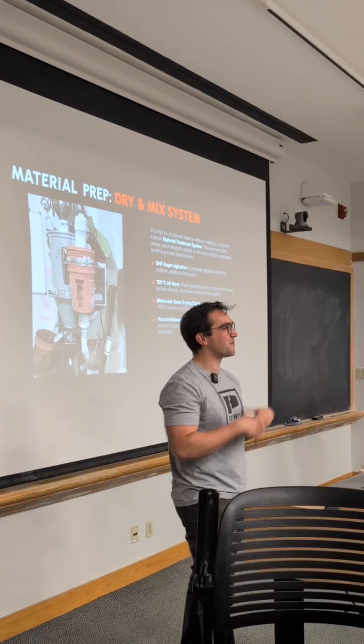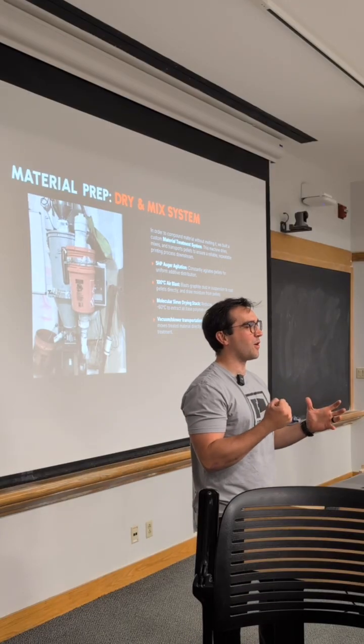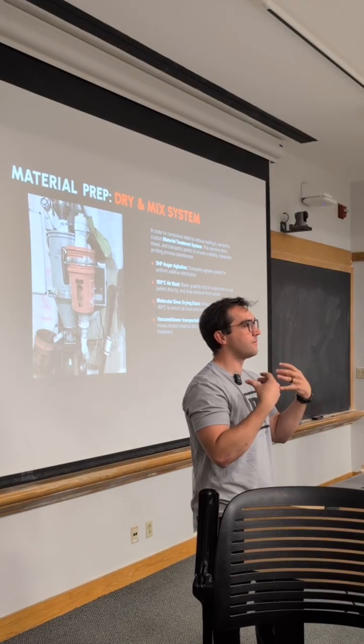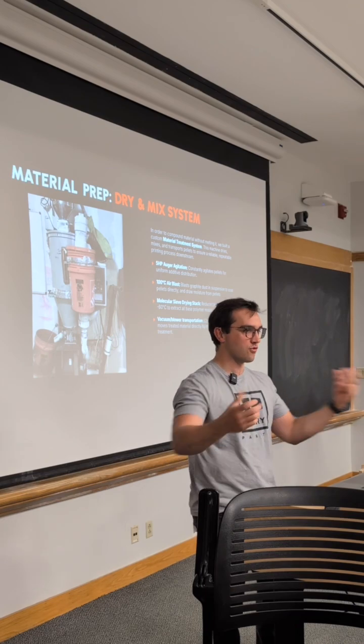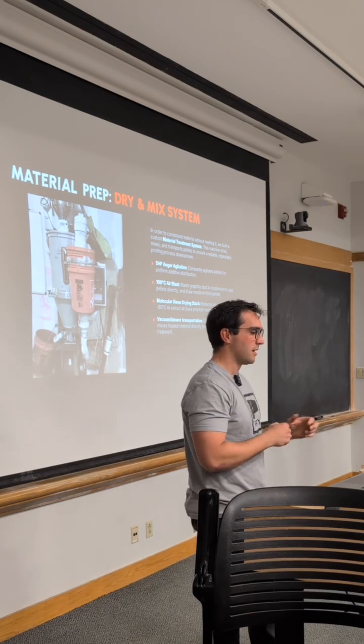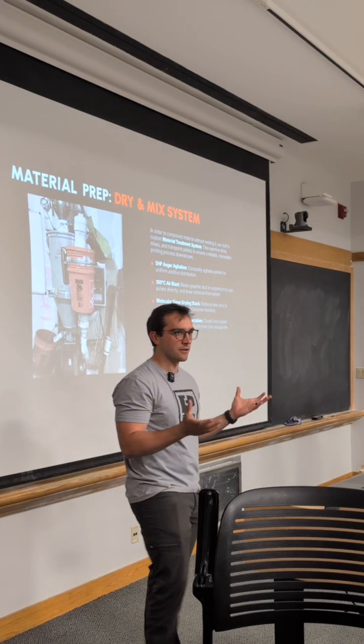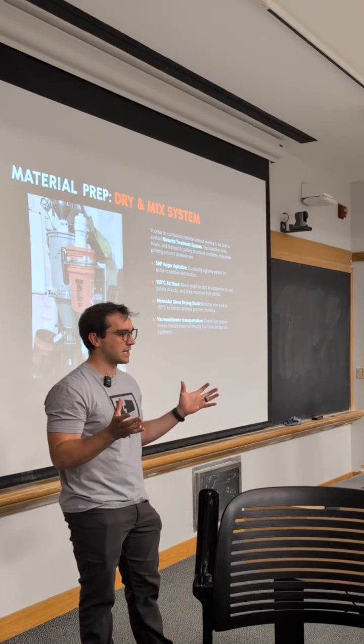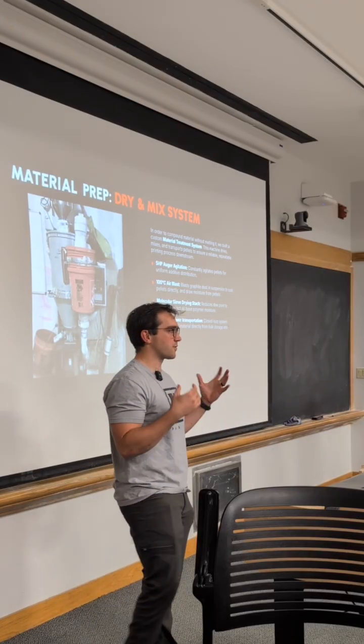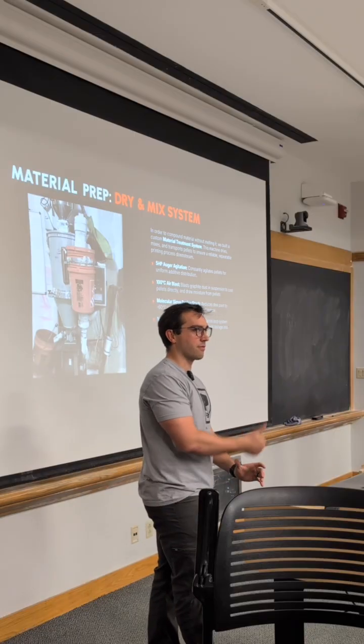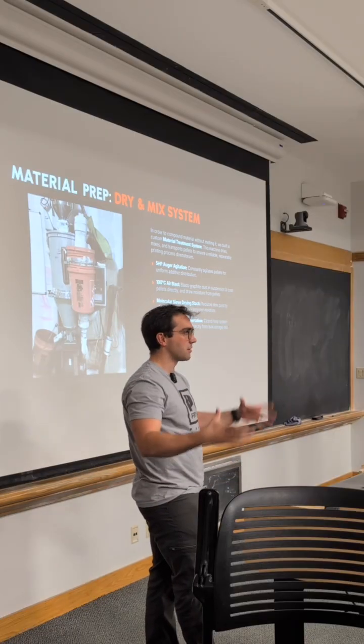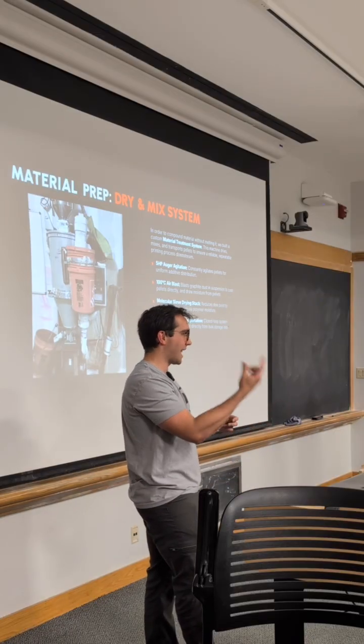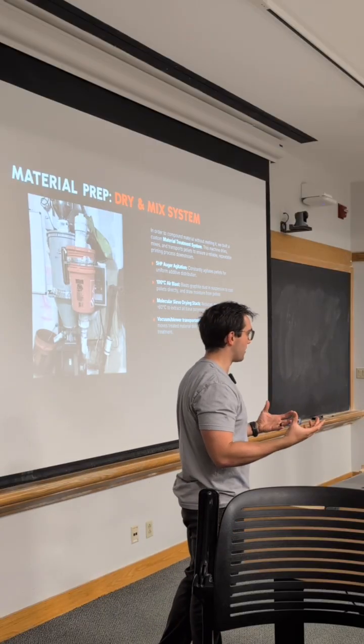There's a large vacuum on the top that pulls all the pellets into the machine. So that's how you feed. You can vacuum distribute your raw material into the machine. It holds about 100 to 150 pounds of pellets at one given time. There's a large 5 horsepower motor running right up through the middle, coaxial with the chamber, and that helps to churn and agitate the raw material while it's in the hopper.